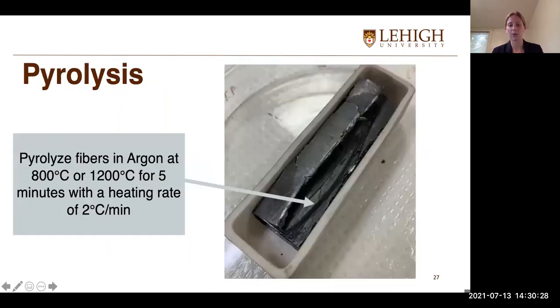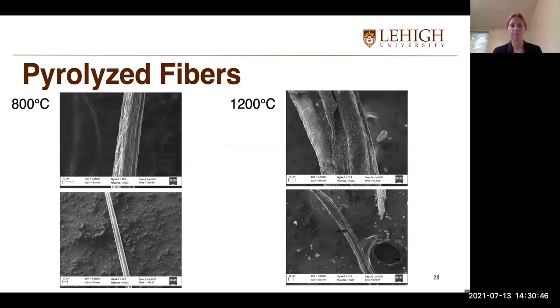So as you can see here, the fibers are still long and they haven't really shrunk a lot. So that was a really good system for that. And for the fibers, I pyrolyzed them in argon again at 800 degrees Celsius or 1200 for 5 minutes, again with a heating rate of 2 degrees Celsius per minute. And so here are some images of the pyrolyzed fibers.